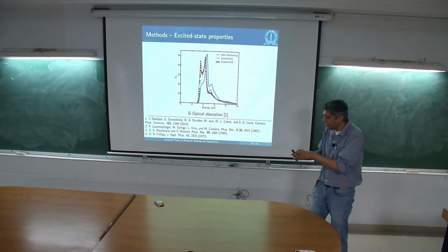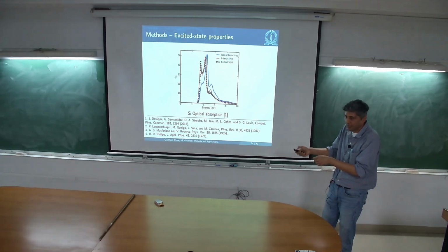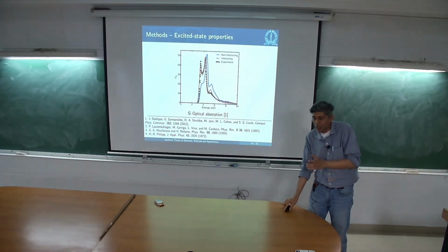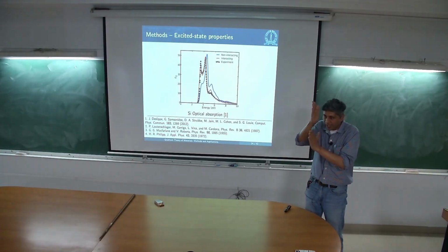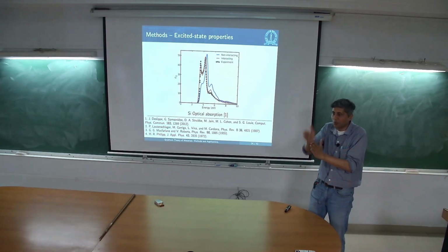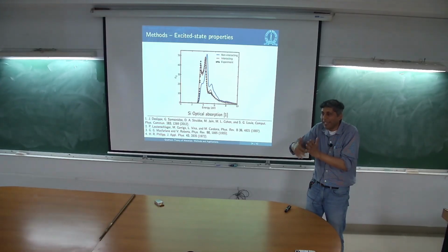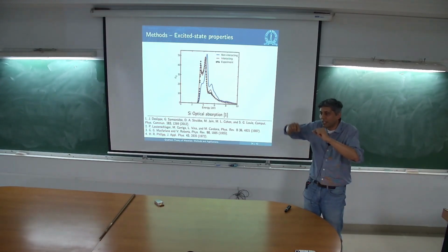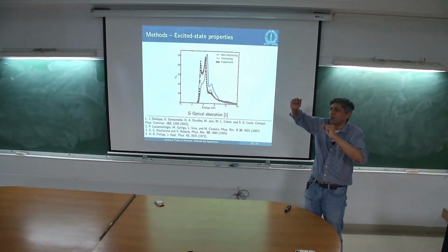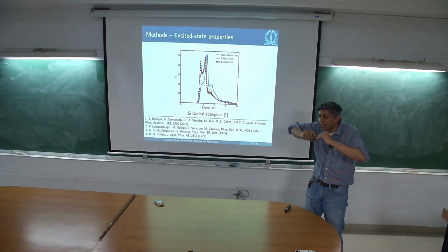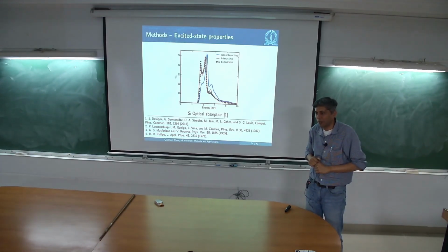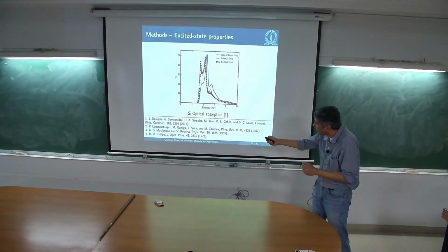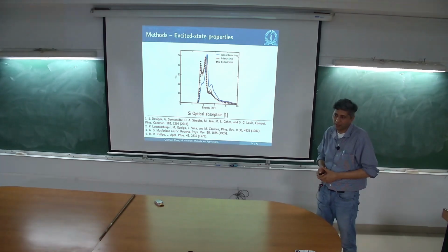So these are excitons which are forming in the system, and at this energy, there is a large density of states of excitons formed because of the electron-hole binding, which you were missing completely in the other case. And when you do this, there are certain parts of the Brillouin zone where you can show that this is where it comes from. In the density of states from this part, you will find that the electron-hole interaction is attractive. Therefore, this peak moves to the left, and you get this entire very nice spectrum.